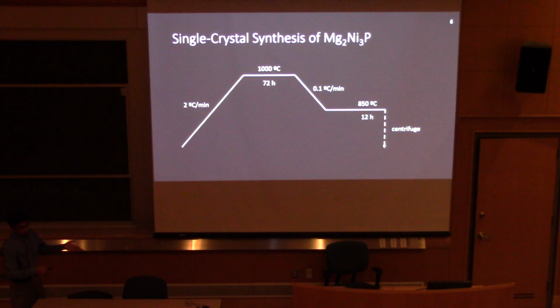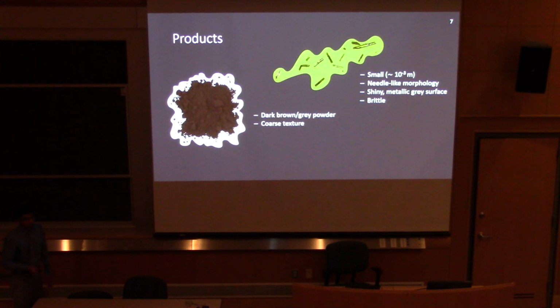So this is, once again, a similar heating cycle, or a similar process. However, I want to emphasize the slow cooling down rate from 1000 C, where everything is in liquid, to 850 C, which is right above the point where it becomes a solid. After which, we centrifuge it out, and then wash it with HCl and water. So over here we have our products.